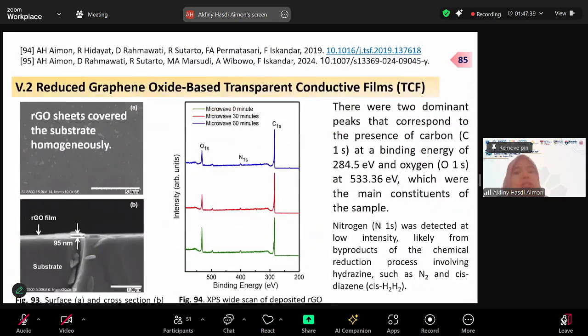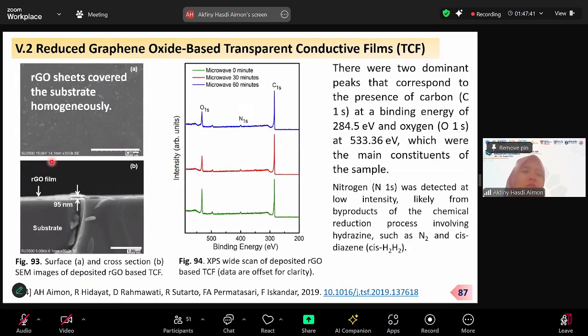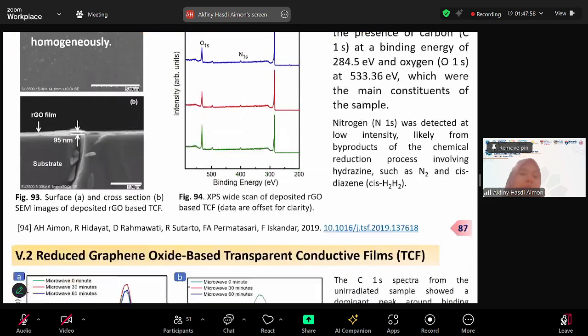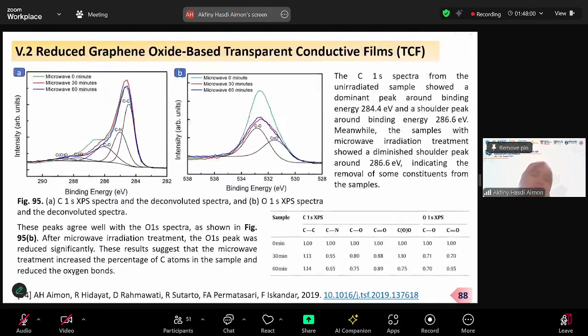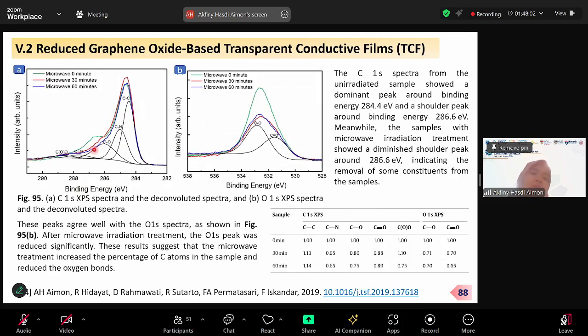Yeah, this is the result that we have. This is our film. It's a homogeneous film, and it has a thickness of 95 nanometers. And it has a carbon peak based on the XPS structure, with nitrogen and oxygen peaks on it. And then we can see about the carbon structure that we have a lot of carbon bonding on it.